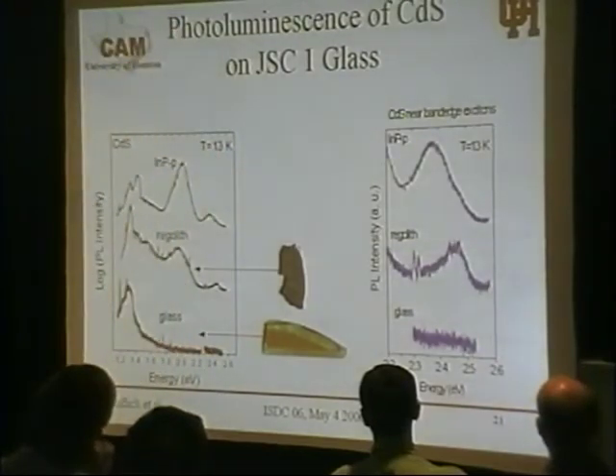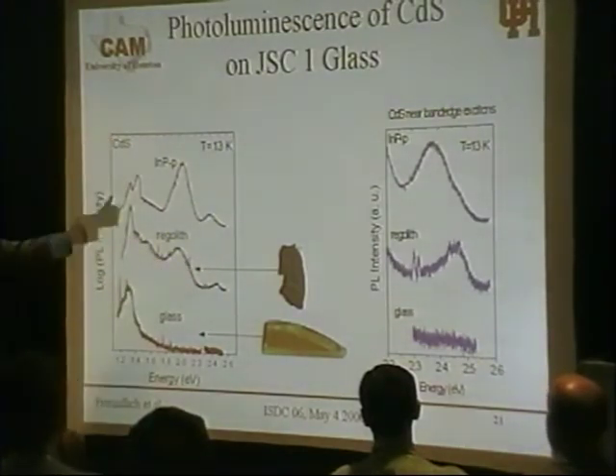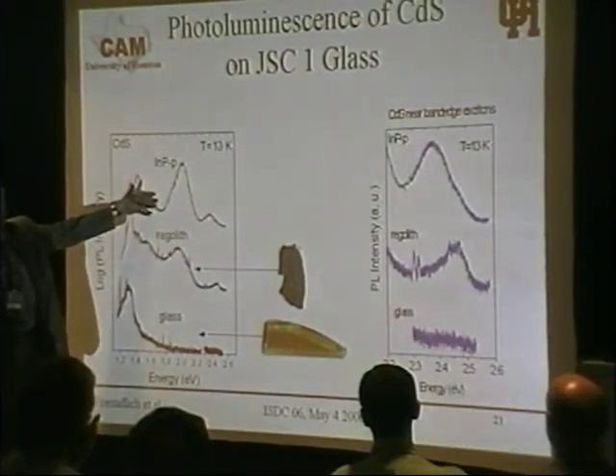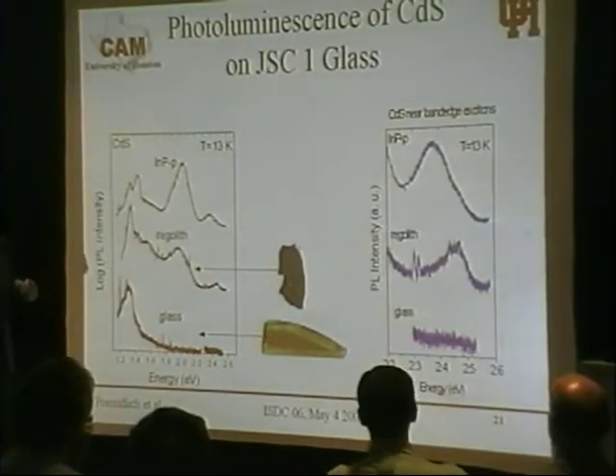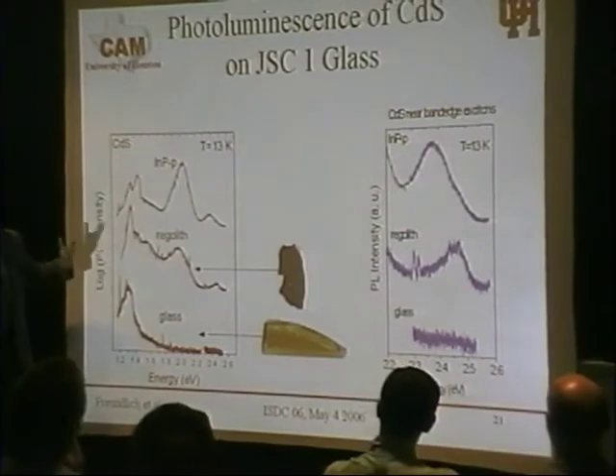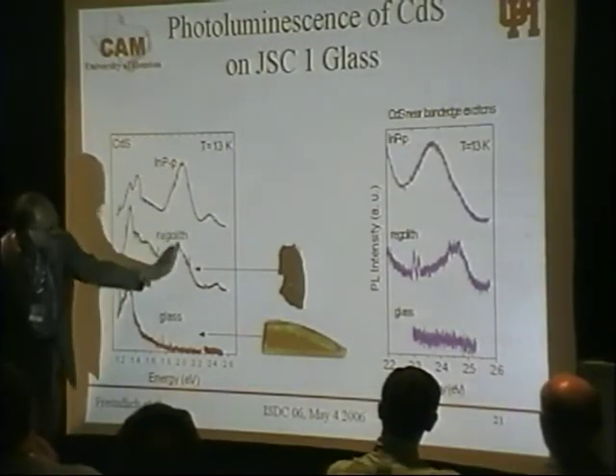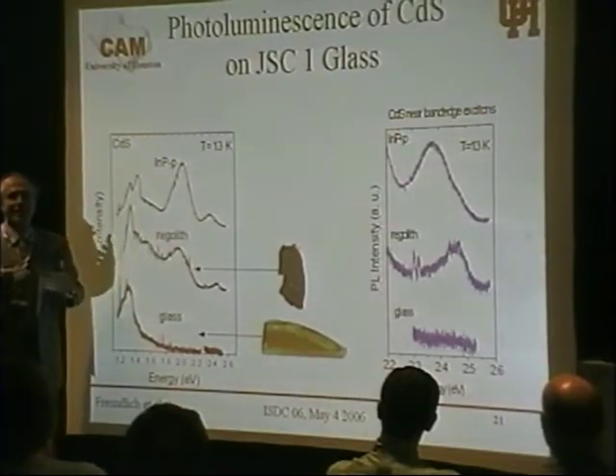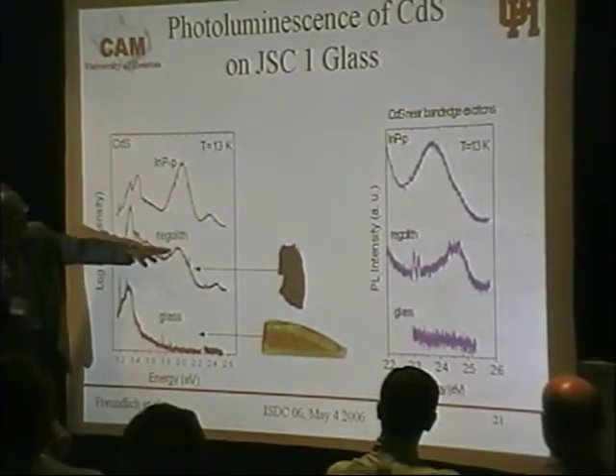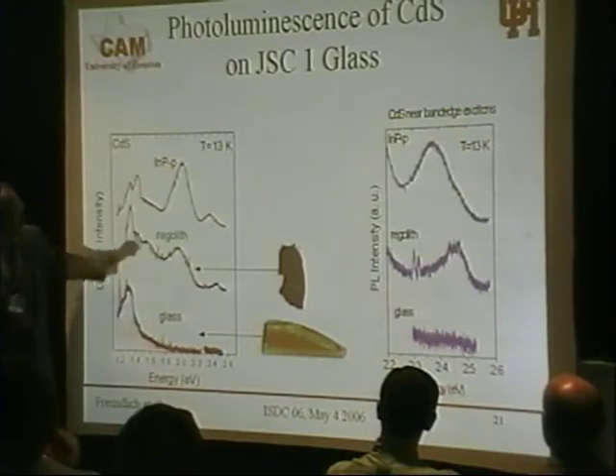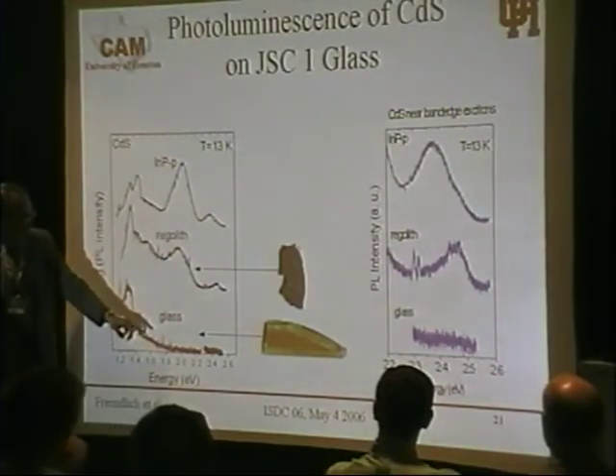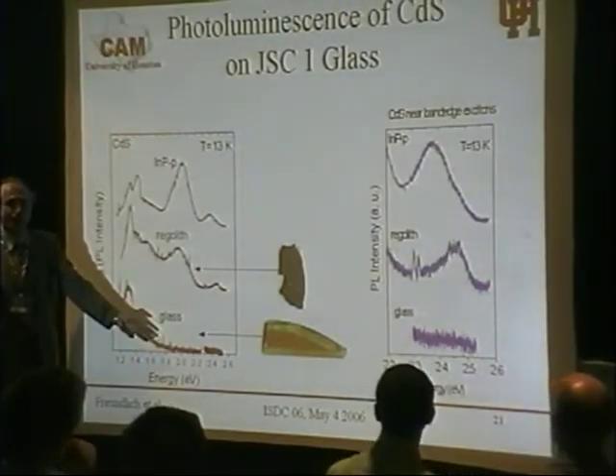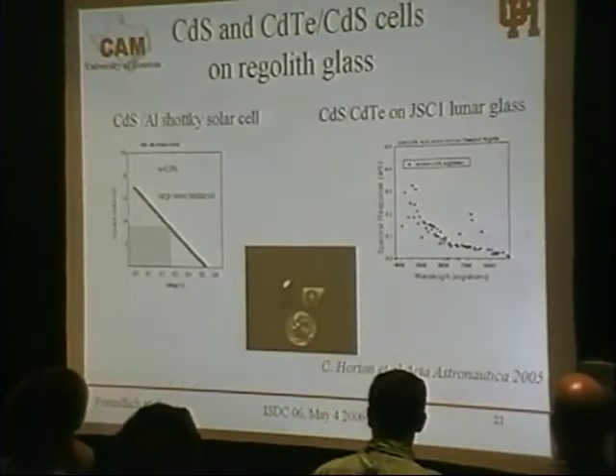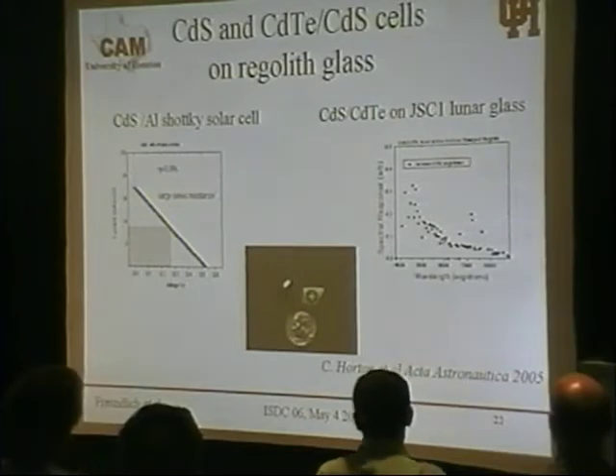The first thing a crystal grower like myself or Alex Ignatiev will do, once you have a substrate, is put something on top of it. We immediately made a comparative study with commercially available glass and the regolith glass we made. This is a single crystal substrate on which we deposited cadmium sulfide. This is photoluminescence, the response of the material to light excitation. Here is the region of excitons, which is a label of material quality. You can see that the lunar regolith is not as good as a single crystalline substrate, but it's better than a commercial glass that we can buy. I'm not going to say who the vendor was. Next.